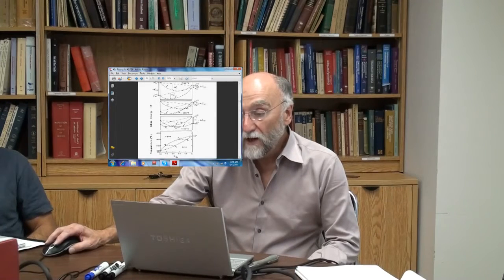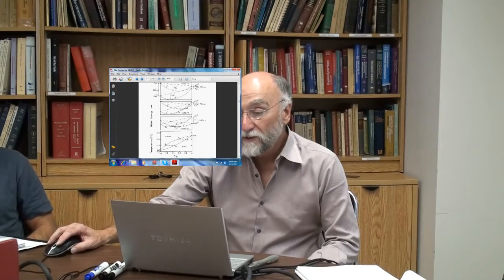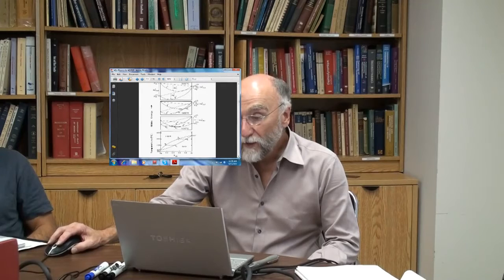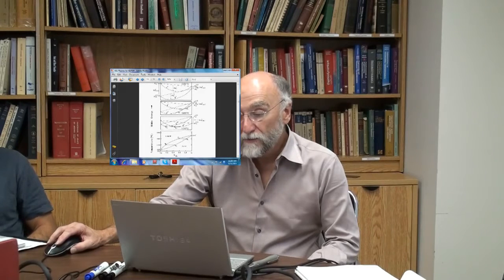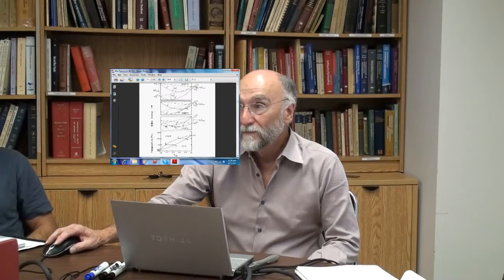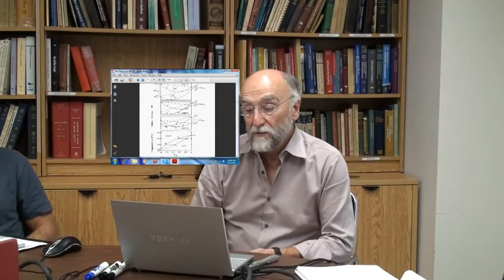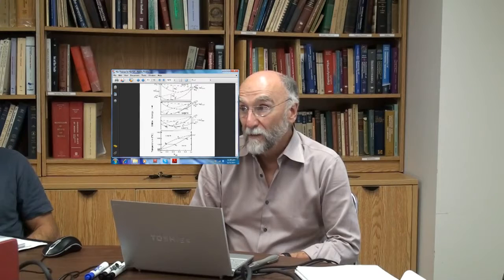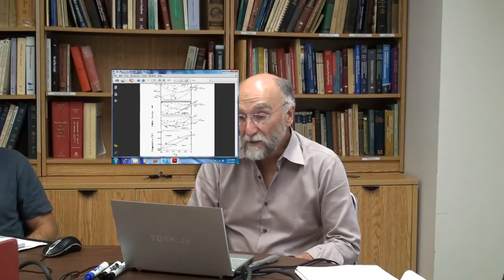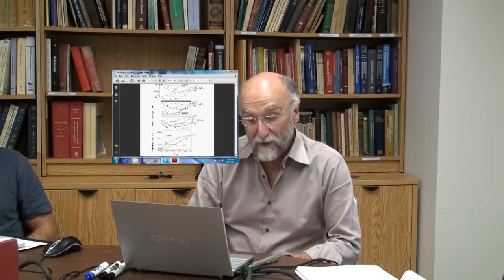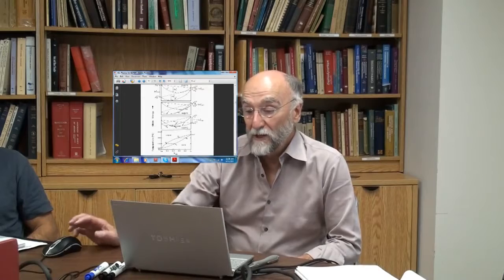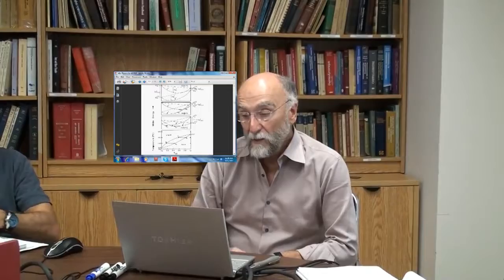and I say that if you draw a common tangent, a tangent to both curves at P1 and Q1, then P1 and Q1 are the liquidus and solidus compositions at that temperature. Now you can look at this as two things. If two phases are in equilibrium, they must have the same chemical potential. The criterion for phase equilibria is equality of chemical potentials. Activities are equal. The chemical potential of silicon in the solid has to be equal to the chemical potential of silicon in the liquid, otherwise there would be a spontaneous transfer from one phase to the other.